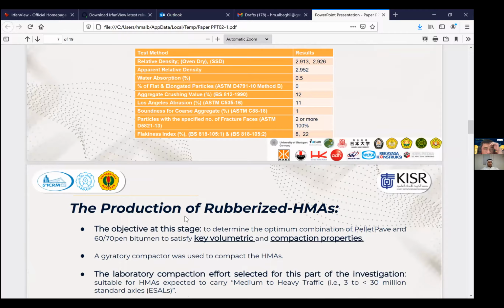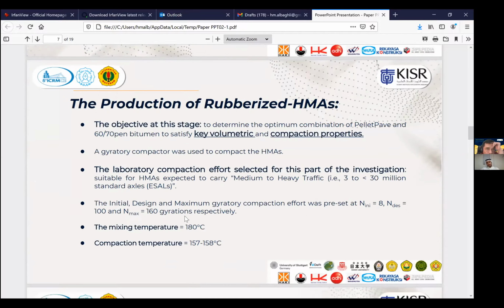Then the next step was to introduce the Pellet Pave plus 60-70 pen-grade bitumen to the optimum aggregate blend to produce the rubberized asphalt. Our objective at this stage was to determine the optimum combination of Pellet Pave and 60-70 pen bitumen to satisfy key volumetric and compaction properties for the new specifications.